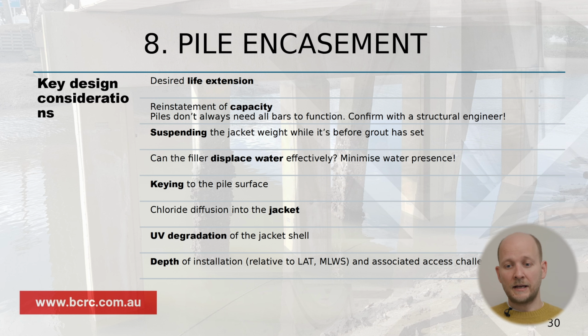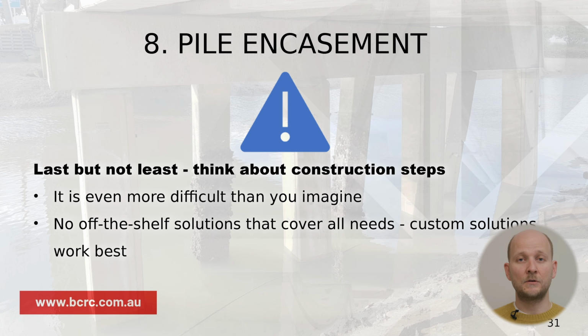UV degradation: like in the example I showed you before, if you install FRP jackets and leave them on, think about how quickly they will degrade under sunlight. So consider coating if you do use FRPs. Depth of installation: I talked about it quickly previously, but make sure that you specify how deep your jackets go. And I would think about lowest astronomical tide or mean low water spring tide, and consider challenges which are associated with it.